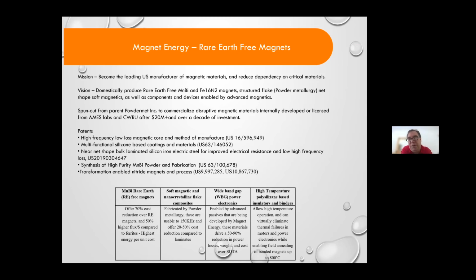Magnet Energy is a new start. We have licensed manganese bismuth technology out of the Critical Materials Institute. Manganese bismuth has no rare earths, and it has the unique structure of having a higher coercivity with temperature, a positive coefficient of coercivity, which means it's extremely resistant to demagnetization at higher temperatures. And it actually has an energy product that can approach or be even better than rare earth magnets at elevated temperatures.